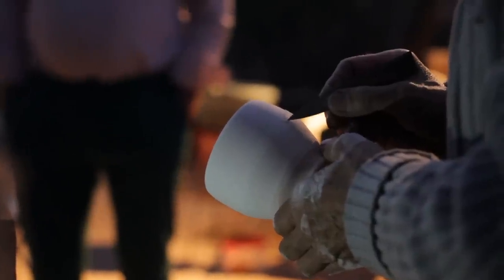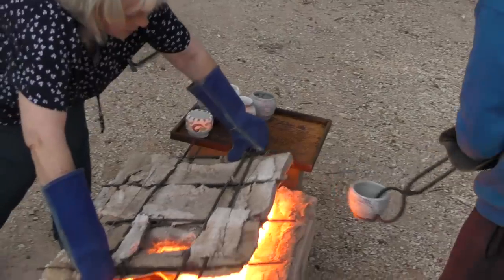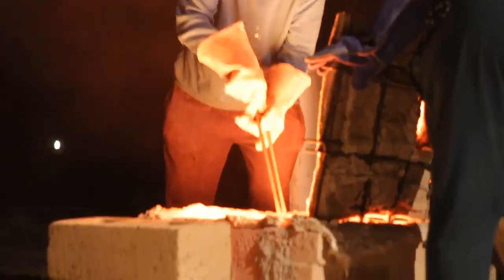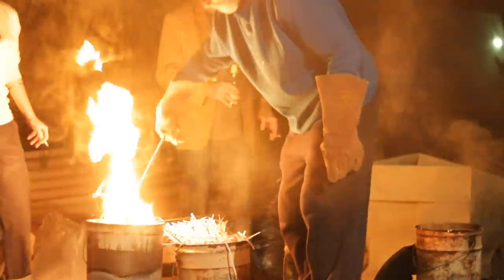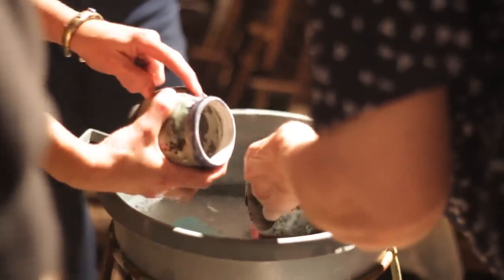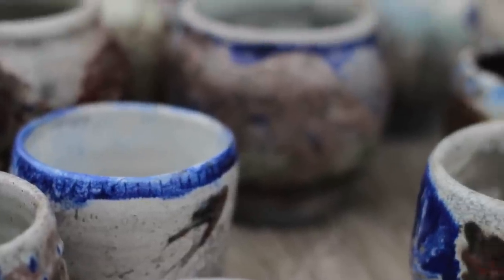After Graham's guests have decorated their pots with scratch designs and various oxides, they go into the kiln - the pots, not the guests - and are left for a specific length of time before being yanked out, spun around, and dropped into cans of burning paper. After a while in the paper they're pulled out and dropped into water to cool, then scrubbed down to remove any loose glaze particles and soot. And after all of that, this is what we get.